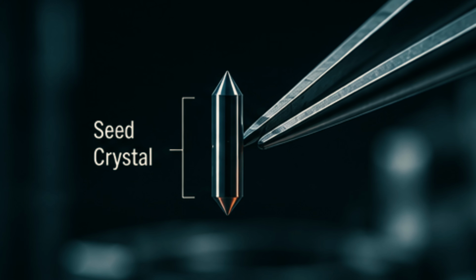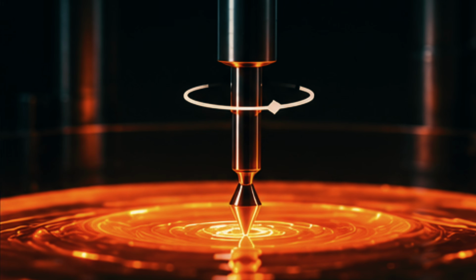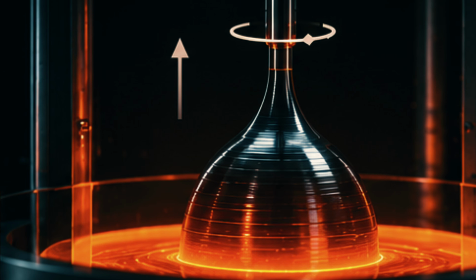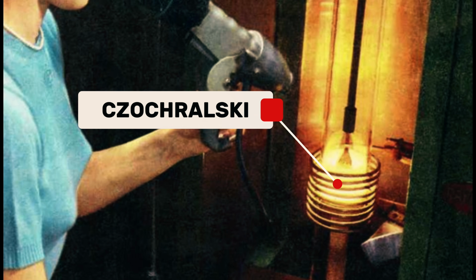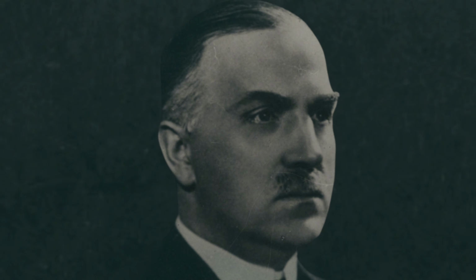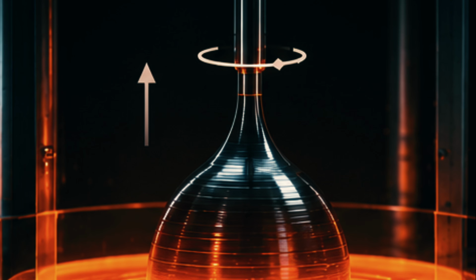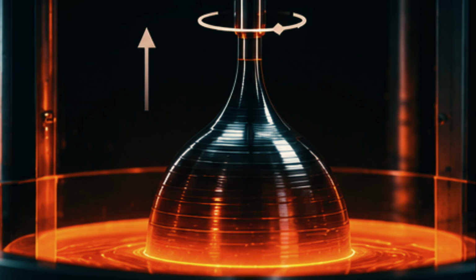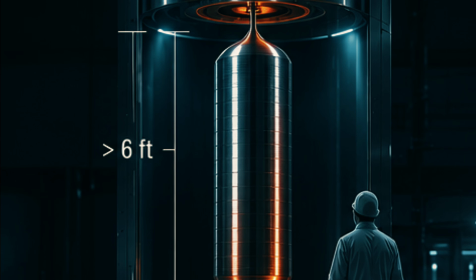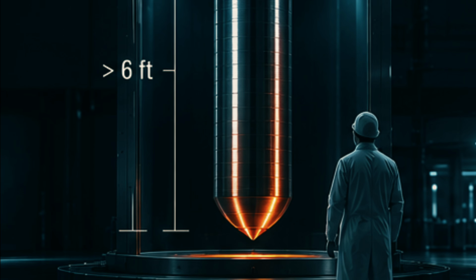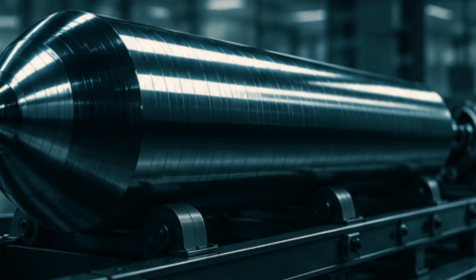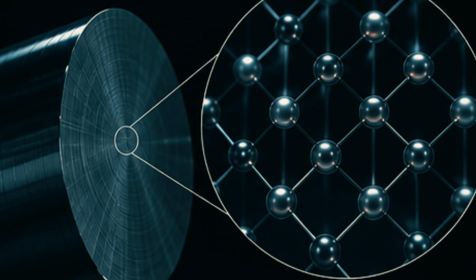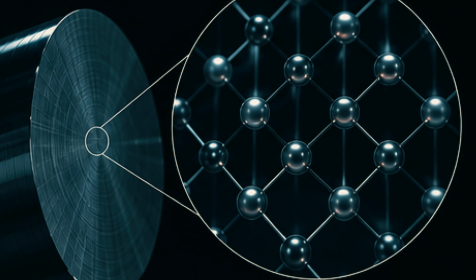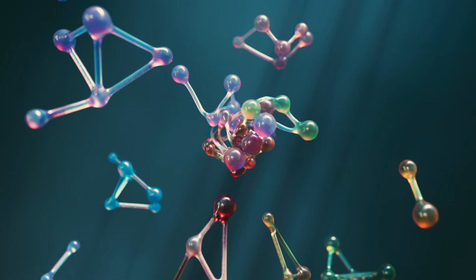A small seed crystal, no bigger than a pencil tip, is dipped into the molten silicon and slowly pulled upward while spinning in a method called the Czochralski process, named after the scientist who discovered it almost by accident a century ago. As it rises, molten silicon solidifies onto it in perfect atomic alignment, growing into a cylindrical ingot that can stretch over 6 feet long and weigh hundreds of pounds. A single continuous crystal, with every atom locked into the same repeating structure from one end to the other.